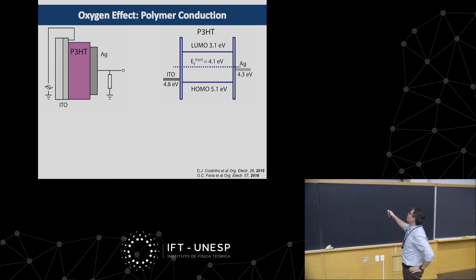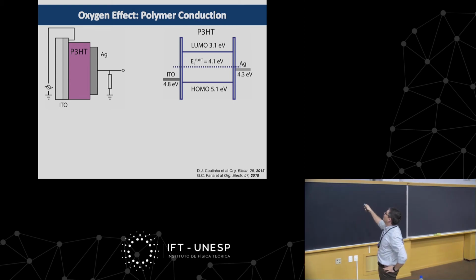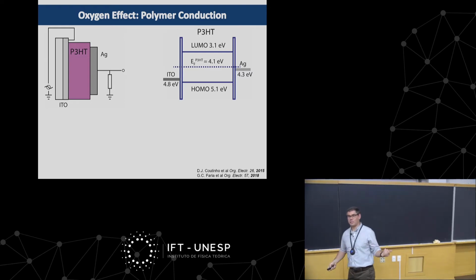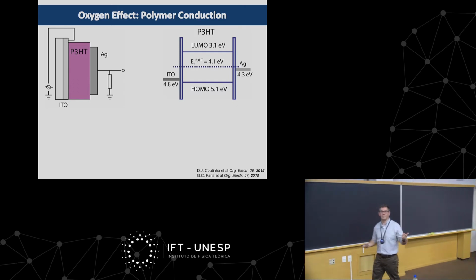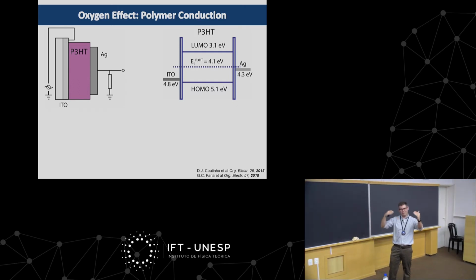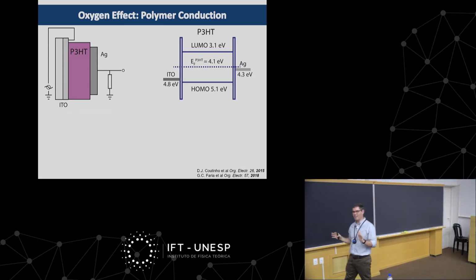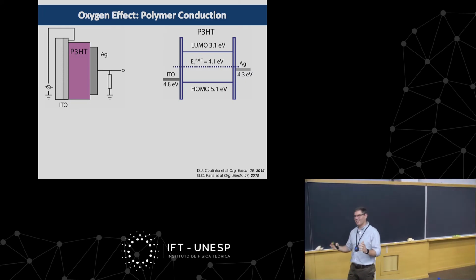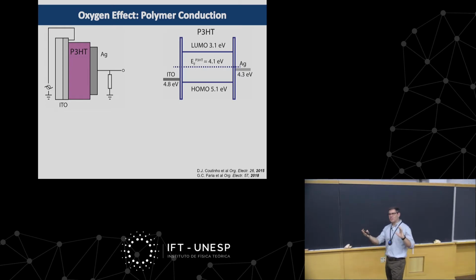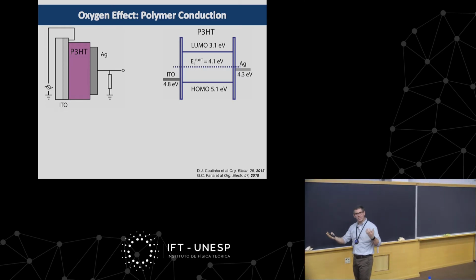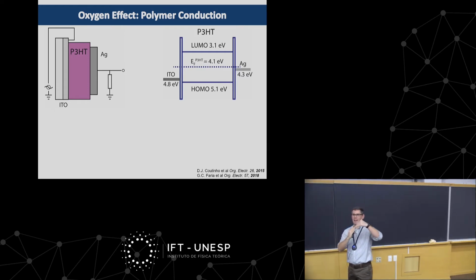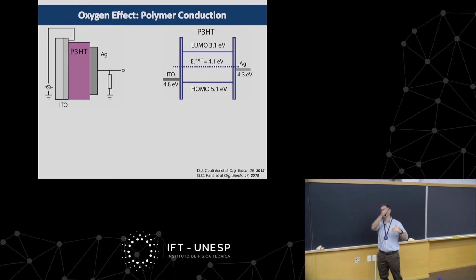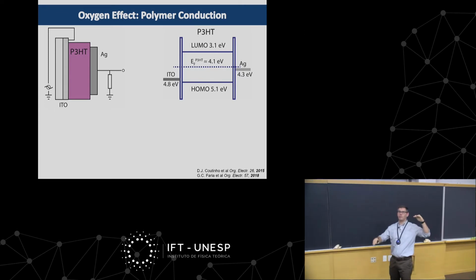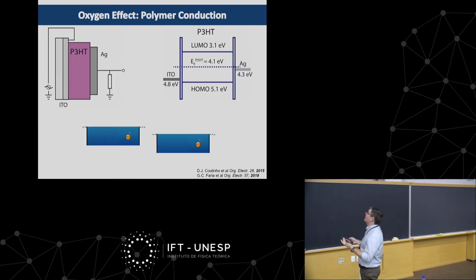the Fermi level is lying in the middle of the band gap. So when you actually build this device, you have a huge difference of energy between the work function of one of the electrodes and the Fermi level of your material. And of course, when you study thermodynamics, you know that those kinds of abrupt changes in energy, nature doesn't like them at all. So what is going to happen? Somehow they're going to exchange charges in order to equalize that interface and have a smoother transition between two different Fermi levels.